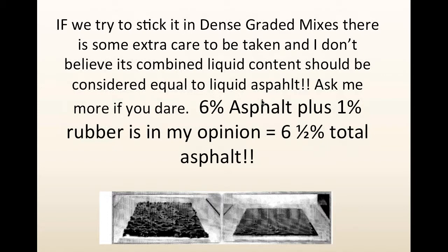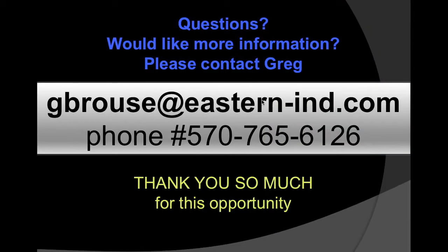But one of the other things that I like to express here that we have to be careful about is when we look at rubber blended with asphalt, it's not 1-to-1. 6% asphalt plus 1% rubber does not equal 7% liquid. I'm going to say it equals about 6.5. That might even be kind. But even with the excess of rubber in there, it's still by and large cost effective. It's still cheaper in the end, as we move to getting rid of the blending cost. And I'm thinking that about covers it.